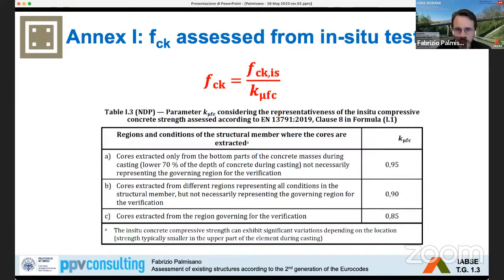And we have a general procedure given in a European standard, EN 13791. There is the necessity to pass from fck in situ to fck, since all the formulae given in Eurocode for both new and existing structures are in terms of fck, because they have been validated for fck and not for fck in situ. This is why in Annex I we have this very simple formula where there is a parameter kappa that is a function of the position of the cores, for example, taken from the structure to make all the tests and to evaluate fck. And we can see kappa varies from 0.85 to 0.95. This means that in some cases, depending on the region where the cores are taken, fck can be very similar to fck in situ, while in other cases, fck can be greater by about 17% than fck in situ. And with this information, I've completed my presentation, and thank you for your attention.